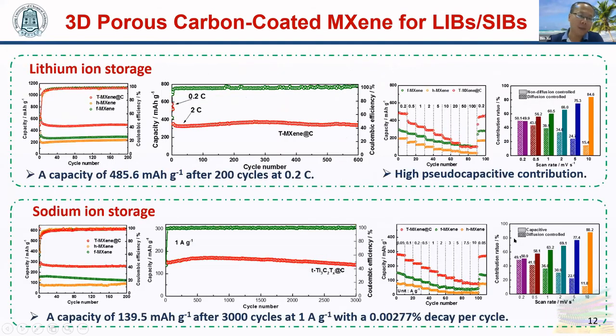This unique structure makes the carbon-coated MXene show very good electrochemical performance in both lithium-ion batteries and sodium-ion batteries. For lithium storage, a capacity of nearly 500 mAh per gram was obtained, with high pseudocapacitive contribution. For sodium storage, a very stable capacity was obtained during 3,000 cycles. A very small capacity decay was observed.